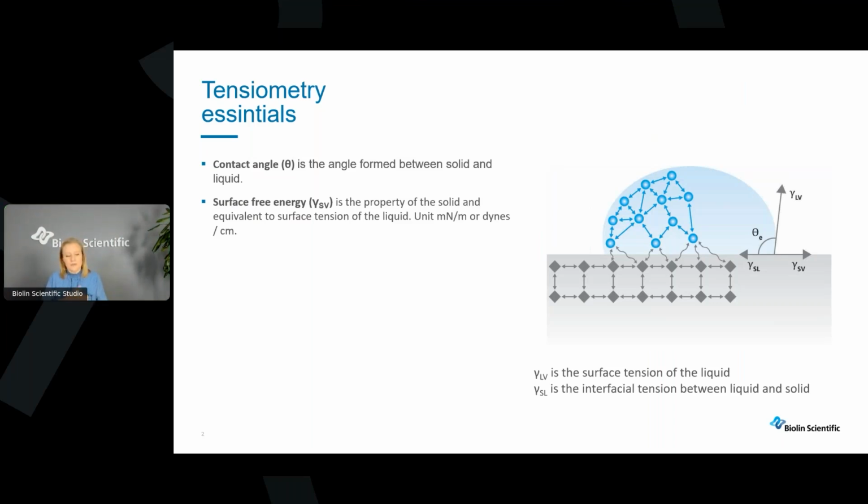So the reason really to measure the surface-free energies is to have some sort of a value that is independent of the liquid, that is just describing the solid in a similar way as surface tension is describing the liquid. So the surface-free energy is really equivalent to surface tension of a liquid, and it actually arises from the same type of molecular interactions.